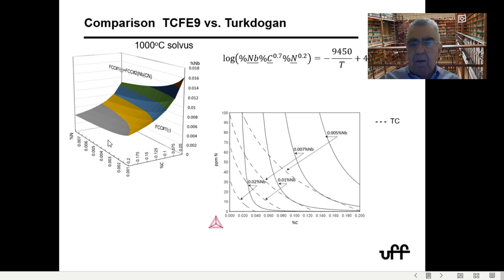And if you project this surface into a plane, you can see that the values for solubility are much different because there's no way you can take into consideration the influence of varying carbon and nitrogen in the compound. So the values predicted by these simple formulas are not very accurate compared with computational thermodynamics. Of course, when Turkdogan and Palmieri did this, it was not very easy to take into consideration all this data. Now the software is available, and you can do these calculations rather easily.